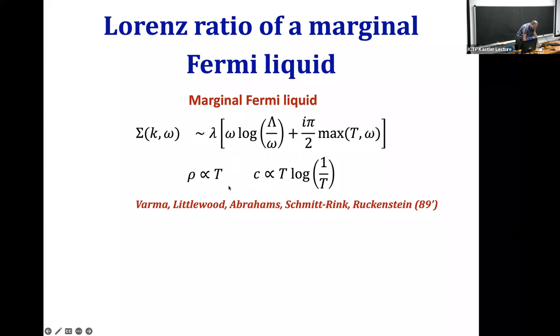Now a couple of comments here. The marginal Fermi liquid is really a phenomenological theory. To make predictions, we really need some model that we can solve that gives this behavior and allows us to calculate any other quantity. For instance, we can write models that give this single particle scattering rate or self-energy, but the resistivity would not scale linearly in temperature because the scattering all comes from small angle scattering. This is actually what happens in the model that Avi mentioned yesterday. If you have a 3D Fermi surface coupled to a critical boson, this is precisely what happens.